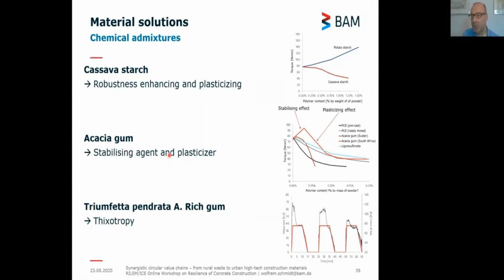It even outperforms polycarboxylate ethers in plasticizing cement and concrete systems. The only problem here, you can see again the torque versus the dosage, and this is a polycarboxylate ether, this is an acacia gum, but the specification is that in the beginning it is stiffening, and then only beyond a certain dosage and also at some critical water cement ratios, they start to liquefy dramatically.